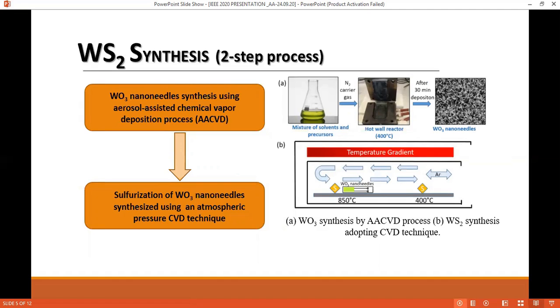In the first step of synthesis, tungsten trioxide nanoneedles were directly grown on commercial alumina substrate via aerosol-assisted chemical vapor deposition process. The substrate was kept inside the hot wall reactor at a temperature of 400 degrees Celsius. Then tungsten hexacarbonyl dissolved in a mixture of acetone and methanol was sonicated and placed in an ultrasonic bath to convert the mixture to an aerosol. Nitrogen gas was used as a carrier to transport the aerosol to the heated zone inside the reactor.